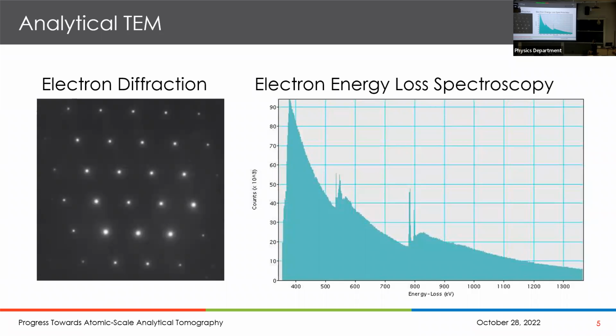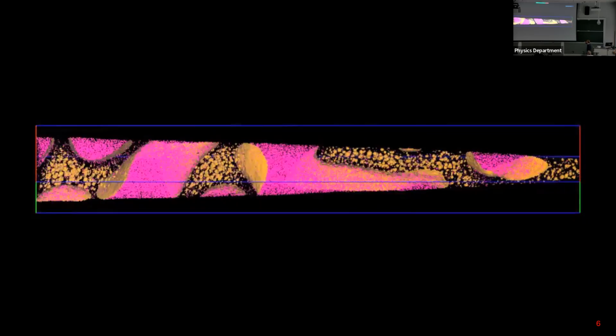And so that's a very important adjunct I'll say more about, but that's part of the analytical part of ASAT. Well, on the other hand, there's the atom probe, and here's a high quality image from a nickel-based superalloy. This is about 100 million atoms in that image. They're not all displayed because it's too much information. But what you can see here are large contiguous phases. This is the disordered FCC phase in the material, and then in between, which is clear, is the intermetallic L12 structure, and inside the L12 structure are a lot of small disordered FCC precipitates.